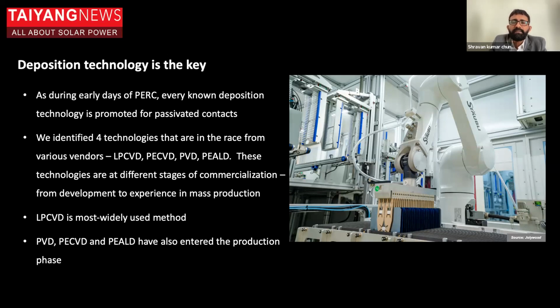So as during the inception days of PERC, when nearly every known deposition technology was promoted for the deposition of aluminum oxide, it's actually happening the same with the TOPCon. So currently LPCVD, PECVD, PEALD, and PVD tools from different vendors are promoted for the core job of producing passivated contact cell structure on the array.